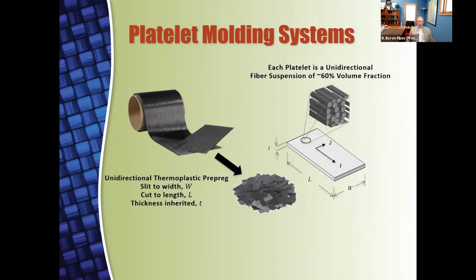The first area that they worked in, well, it isn't the first area they worked in, but it is an area that Boeing supported us for some time, in which we've made some very significant contributions, I think, these students, is in platelet molding materials. Here we take thermoplastic prepreg, we cut it into pieces, we call them platelets, and we then mold them into shape to make complex shapes. This gives you high fiber concentration, moldable material that cannot be made any other way. We can have fiber volume fractions of 60%.